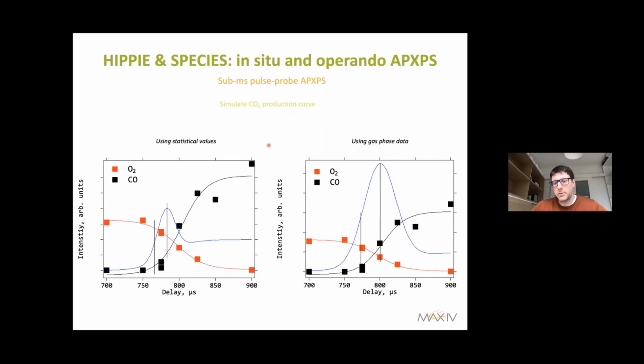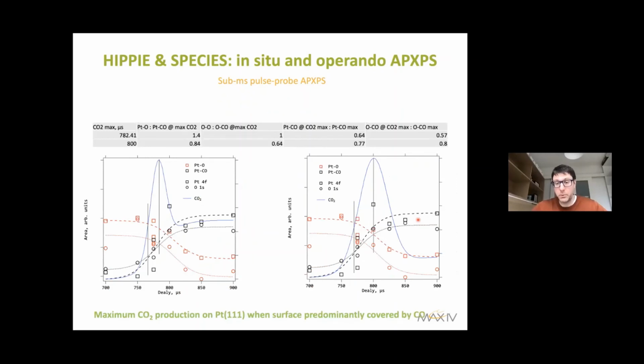And then using either gas phase data or that table that you saw before, you can position the production of the CO2 peak somewhere here. And in reality, the difference is so small that it's practically negligible. So CO2 is being produced where CO and oxygen in the gas phase are approximately the same, and it pretty quickly stops while you have CO-rich conditions. Now we can put here our surface data, shown by squares and circles here. And again, the difference between the two graphs is that we are using the gas phase data or the statistical data. That's the correlation we would really like to see.